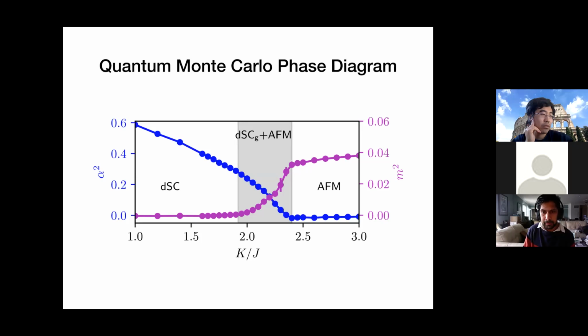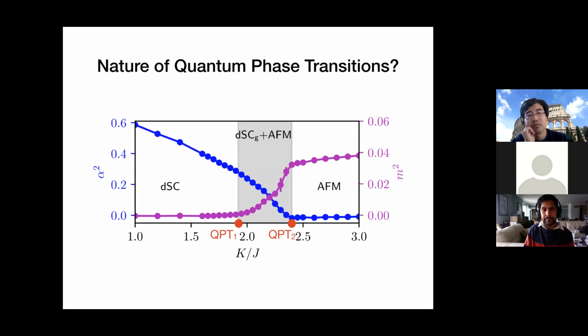So there are two quantum phase transitions, one from the D wave phase to the gapped superconductor plus antiferromagnet, and the other to the antiferromagnet. If you look at the second transition first, this is just 3D XY, obviously, because there's nothing else happening. The antiferromagnet part is already there, spin rotation is already broken. The charge is this U(1), so you get a 3D XY transition.